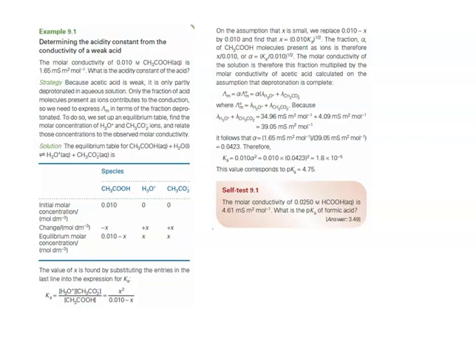So we set up this ICE table, and we have our initial value set at 0.010 for acetic acid, and initially, because there hasn't been any opportunity for it to dissociate, our acid and conjugate base measurements are zero. And then the changes are all 1:1:1, so it's minus x for our reactant and then plus x for our two products. And we can find our equilibrium molar concentrations by the difference between our initial and change magnitudes. So the value of x is then found by substituting these terms into the expression for Ka. So we'll get x squared over 0.010 minus x. And on the assumption that x is small, we can replace 0.010 minus x with just 0.010 and find that x equals approximately (0.010 Ka) to the half power, or the square root of 0.010 Ka.